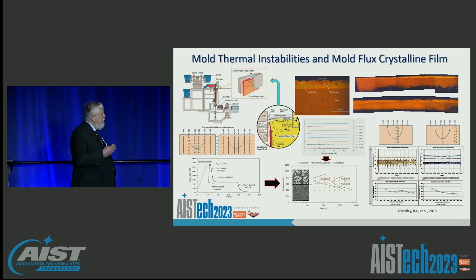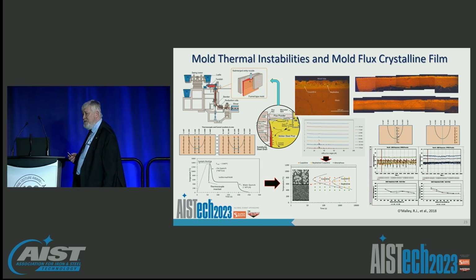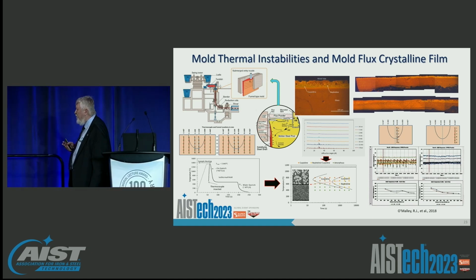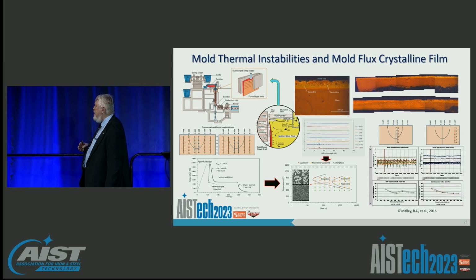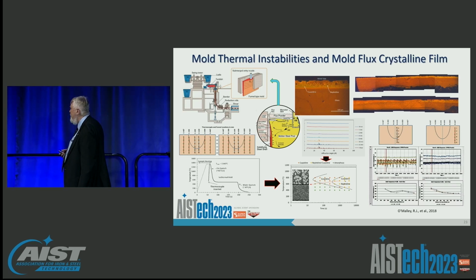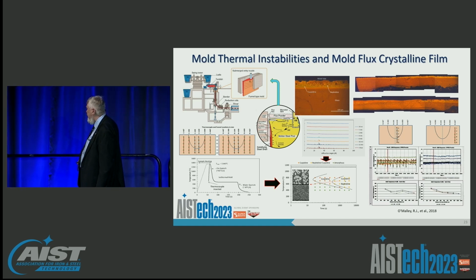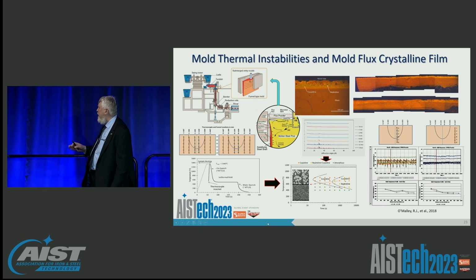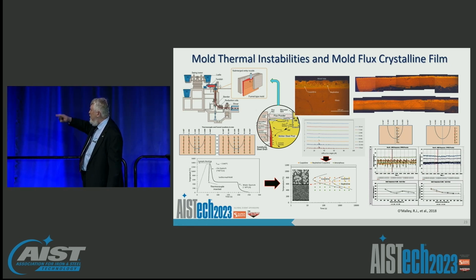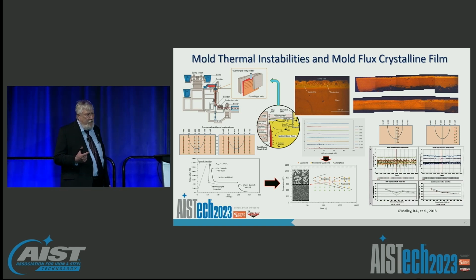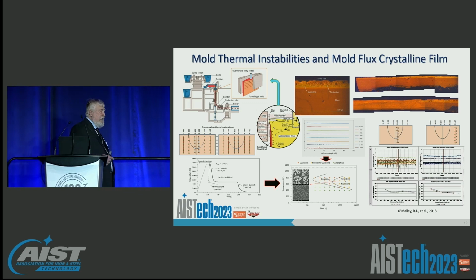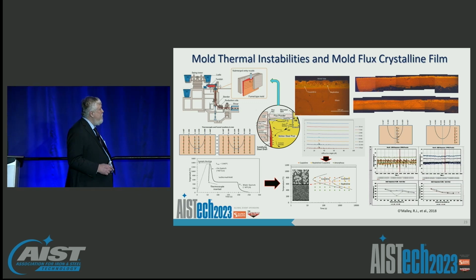So in my past, we've used traditional thermocouples to monitor the stability of the continuous casting process. And in that work, we've actually identified some key mechanisms that create instabilities. And this is an example of a thin slab mold where the funnel area, actually, let's see if I can get that pointer to show. I guess it's not. Anyway, in the lower right, you'll actually notice that there are some fluctuations in temperature that show a sawtooth type pattern low in the mold that is existent only in the root area of the funnel. Outside of that area, the temperatures are very stable.